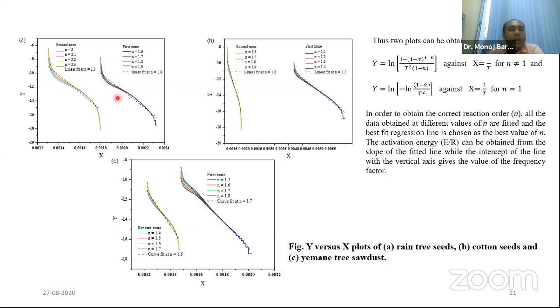Using the graphical method, we can find the slope of the best linear fit line for different values of n, and by estimating the slope of this line, we can determine the activation energy E, because this slope is given by E by R only. So this is how we find the kinetic parameters such as the activation energy by estimating the slope of this curve, and also the pre-exponential factor A, or the frequency factor. That can be obtained from the baseline where it intercepts the y-axis, and by estimating the interception point, we can estimate the value of A, the frequency factor.